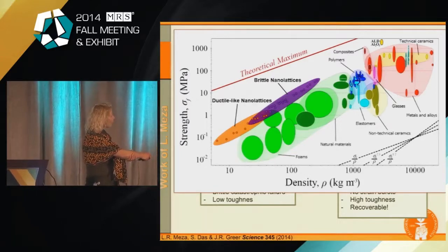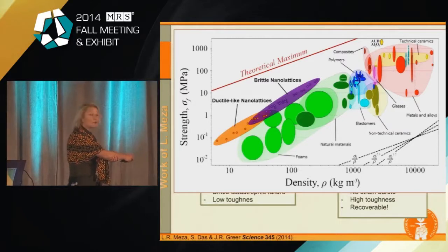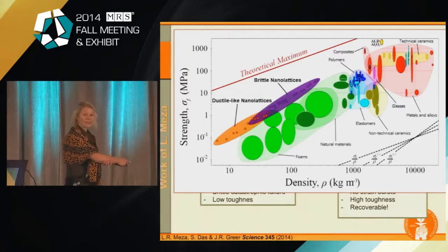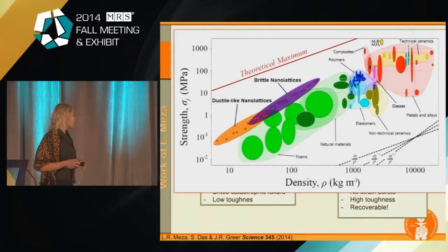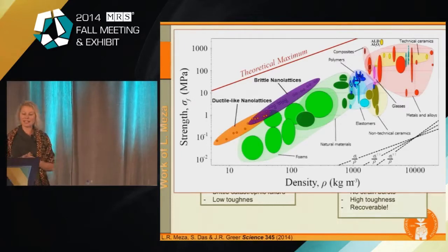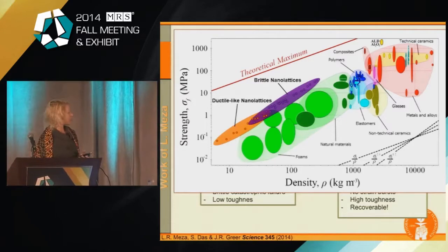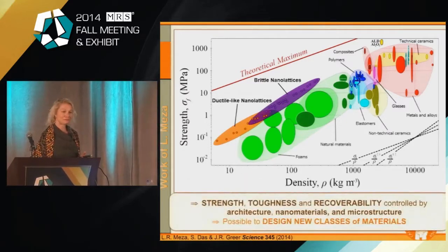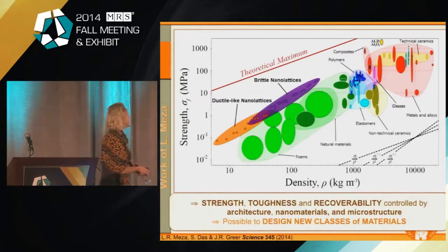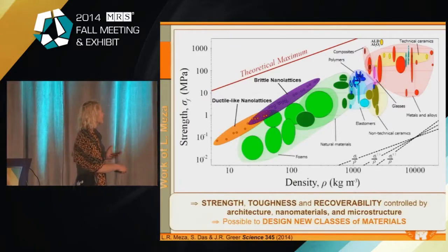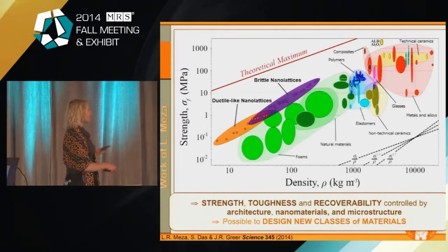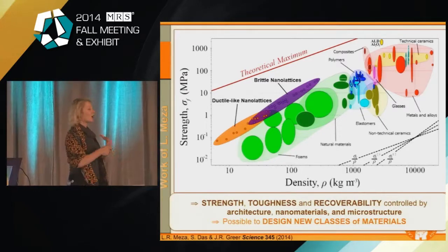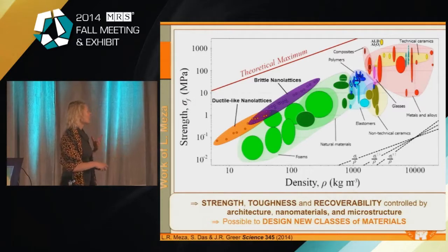So what we're showing is that, sure, we're not quite up here yet, but we're getting really close to it. We're already pushing the boundaries here, pushing the envelope into this white space. And not only that, but it turns out we've actually made some of the most lightweight and strongest materials that exist today. Now, does anybody want to know why this happened? Okay, good. So let me just summarize what you observed. What we are showing here is that the strength, the toughness, and the recoverability can be controlled by the architecture, the fact that these are nanomaterials, and the microstructure together in concert.